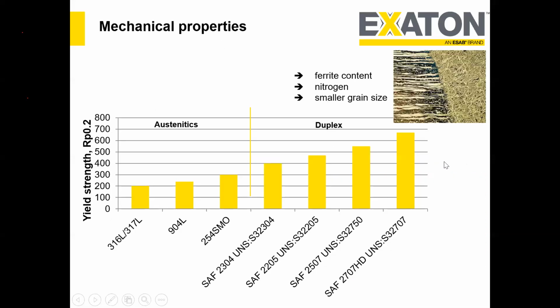These are the mechanical properties of austenitic stainless steel, specifically the yield strength. We see here the 316L around 200 MPa, whereas duplex is more than 400, super duplex is around 520, 550, and hyper duplex is more than 600, around 650. So even the 254 SMO or 904L, super austenitic stainless steel, is also lower in yield strength compared to any of the duplex family.